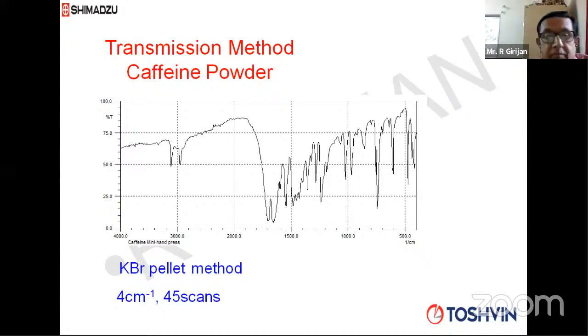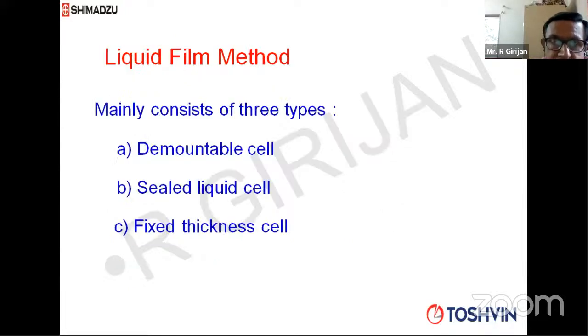This is the transmission spectrum of caffeine powder. We prepared a potassium bromide pellet. We took 45 scans. The scan was repeated 45 times, and the time taken was about 1 minute. And when you take more scans and go for averaging, your signal will increase, noise will decrease. That means the signal to noise ratio will increase, your sensitivity will increase. So, okay. Now, when you come to the liquid film method, for liquid samples, there are 3 different types of cells.